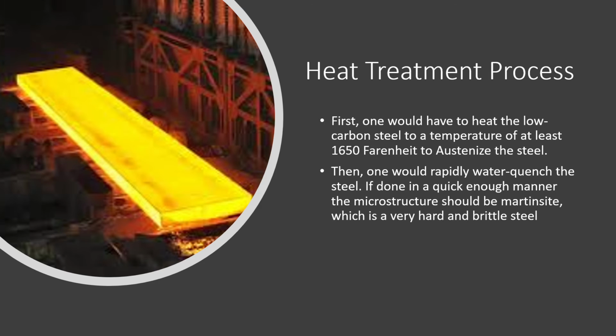Now, the process for heat treatment first begins with bringing the low carbon steel to a temperature of 1650 Fahrenheit to austenitize it. And then after reaching this temperature, you must rapidly water quench the steel to bring it down to a relatively low temperature, leaving you with a martensite microstructure, which is a very hard but brittle steel.